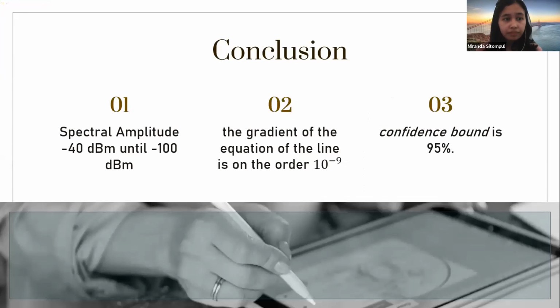Okay, the last is the conclusion. First, based on the results of measurement and signal processing obtained around the location of the Timor National Observatory using a horn antenna, the spectral amplitude at measurement radii of 1 kilometer to 3 kilometers along the same line and direction did not differ significantly, in the range of minus 40 to minus 105 decibel. This states that in the vicinity of the measurement area, there is no material that interferes with electromagnetic signals from the atmosphere.